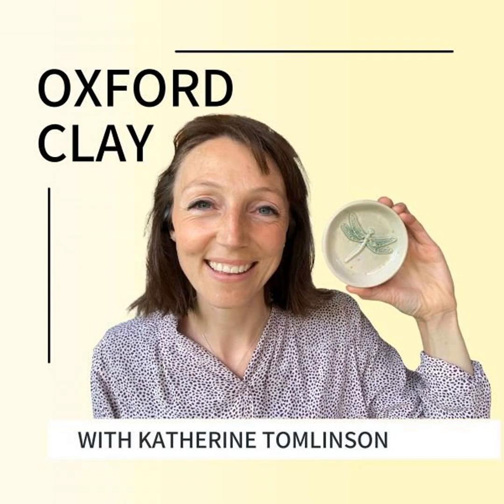They have it in stock. They make it up with the right chemicals and stuff, because you need a chemical in slip called a deflocculant to make the clay runny. So effectively what you're doing is you're making a sticky clay, and then you're adding a chemical called a deflocculant. I use sodium silicate, and I put hardly any in, a few drops, a tiny bit, and it's incredible. It turns the clay from a sticky, hard clay substance into this beautiful flowing liquid that you can then pour into molds for slip casting.